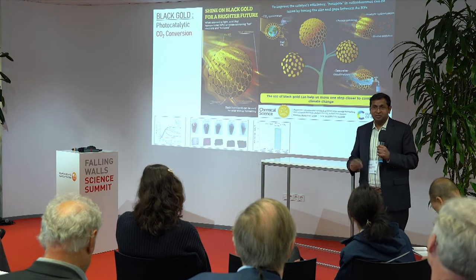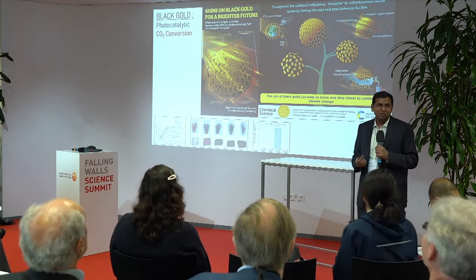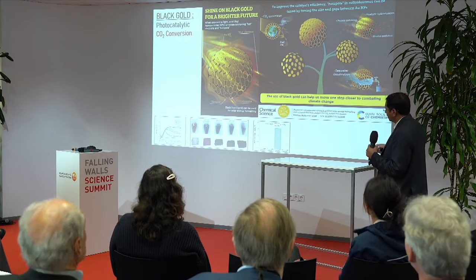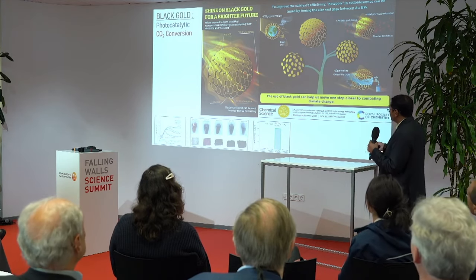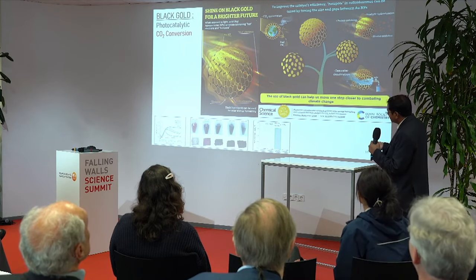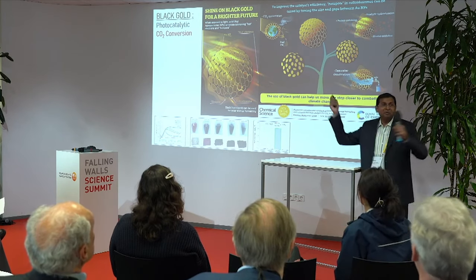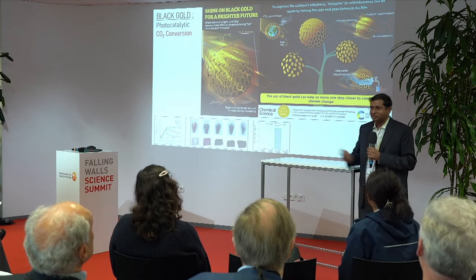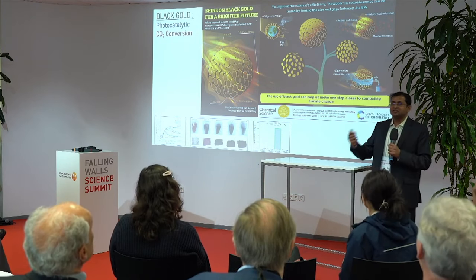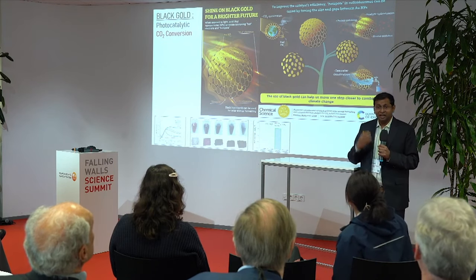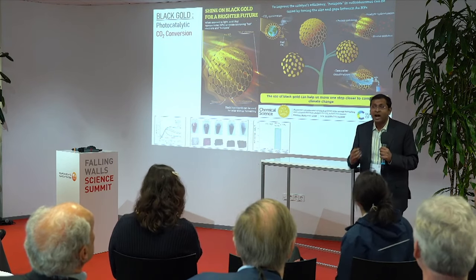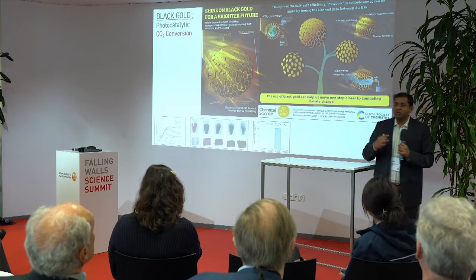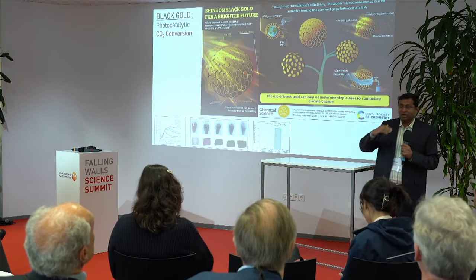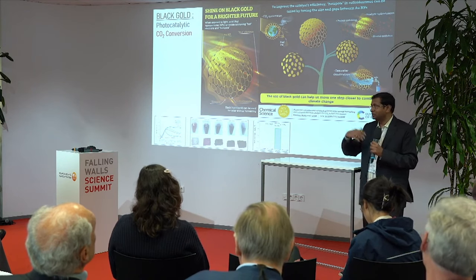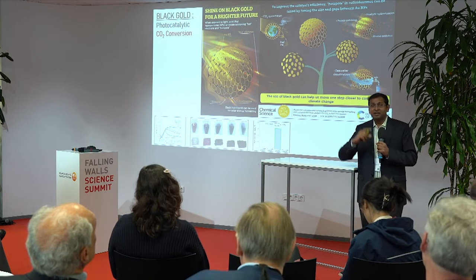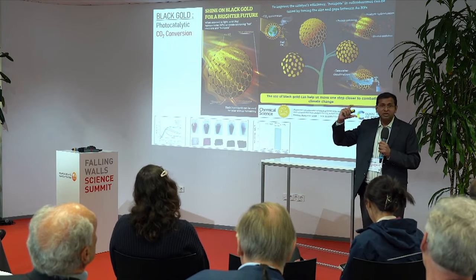I said, okay, now we have a material which should act as a very good catalyst because it is harvesting lots of photons. But when we did the catalysis, although we see the activity, say, better than reported in the literature, if you look at the number, it's 1.5 micromole per gram. And we're talking about 40 gigatons of CO2 per year. So there's no correlation. So then we asked this very basic question: if I have a material which can harvest so many photons, then why is it not active? Then we realized it's not only about harvesting the solar photons, but also about, once you create these excitons, as one of the speakers explained, the lifetime of these electrons needs to be good, right?